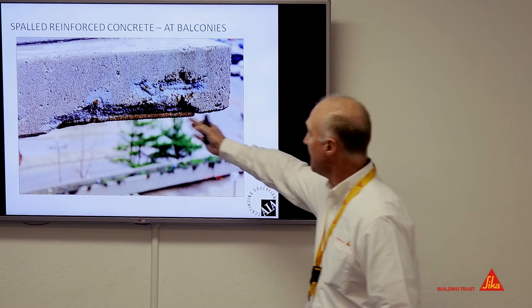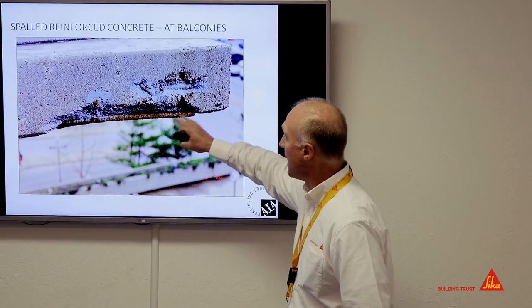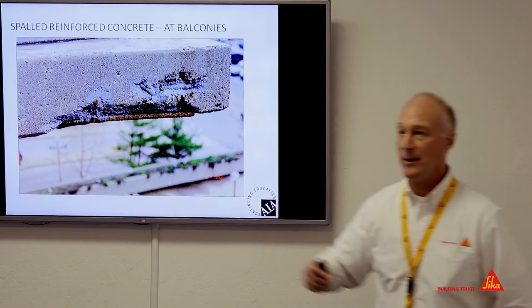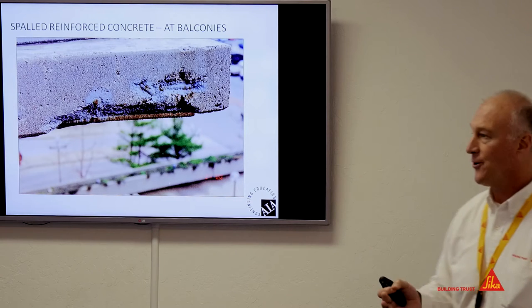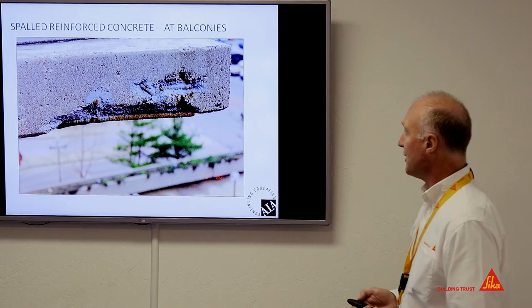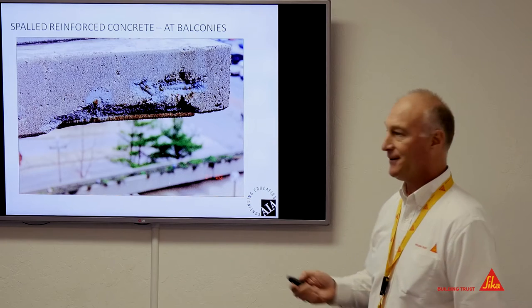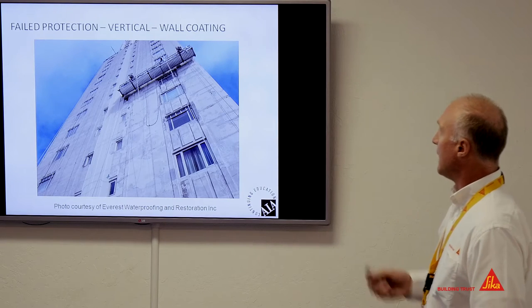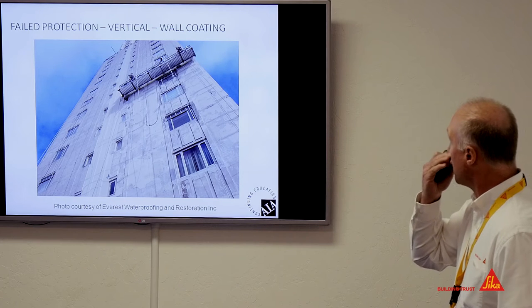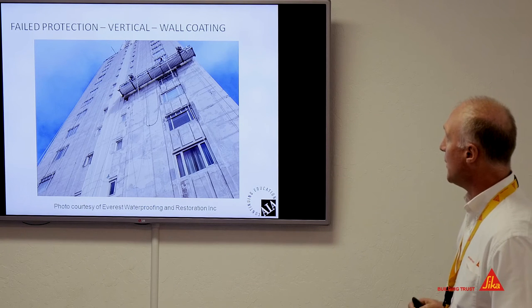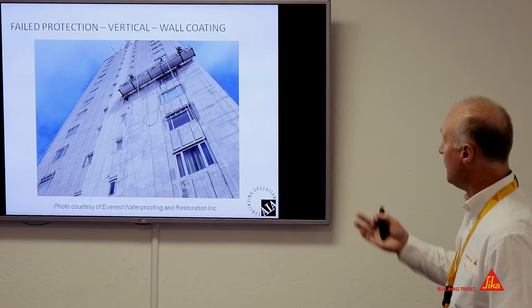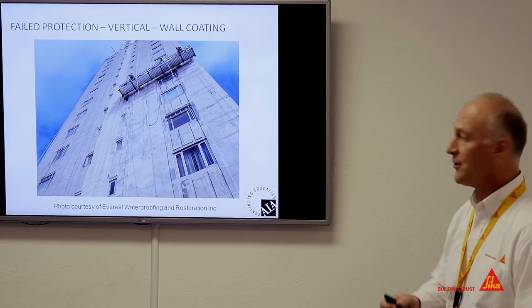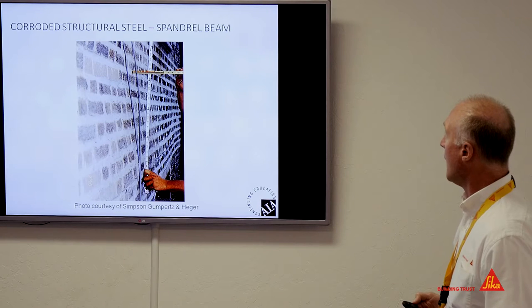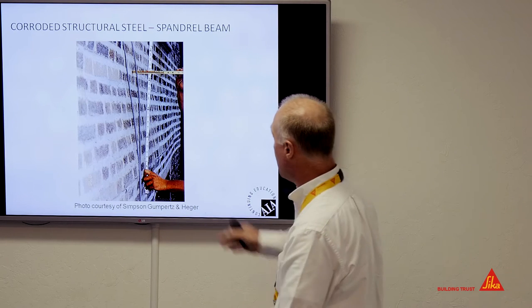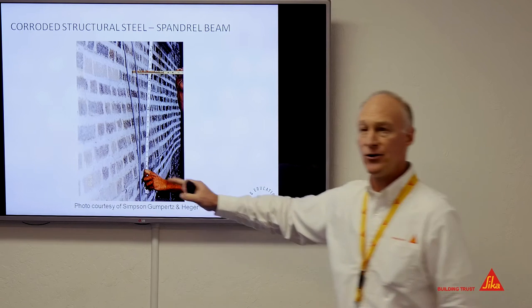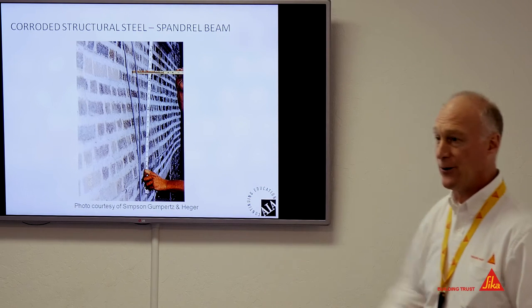And here you could see, in this case, an owner tried to buy a little bit of life by spray painting a little bit of paint on the rebar in hopes that maybe that would slow the corrosion down. But in reality, it really didn't provide any protection to the steel. And just touching on, this is a coating removal that was taking place at 1101 Green Street. Due to what I call a failed coating, but they had other issues there, which I'll touch on as well. And then Graham will spend his time on this, but I had some photos and I thought I would put them in here just to whet your appetite as to what you'll see with Graham's presentation.